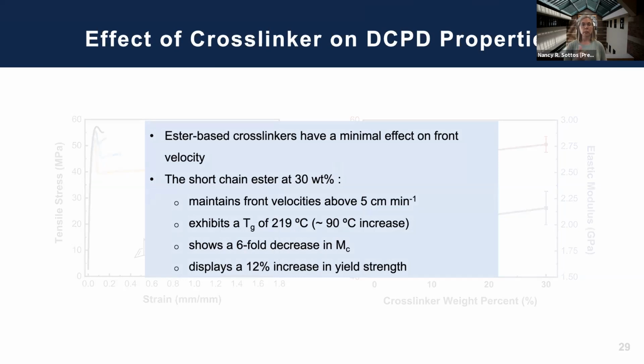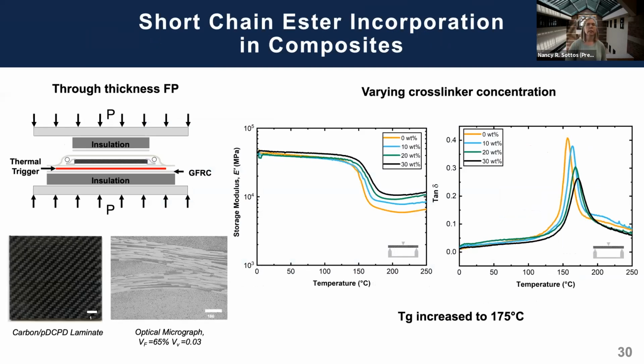on front velocity, which was an important element of this study, because everything you add to the system could take away from the frontal polymerization process. And we are able to get these high TGs and increases in stiffness and yield. We then incorporated the short chain ester into a composite, which was no small feat since we're synthesizing this all here at U of I.